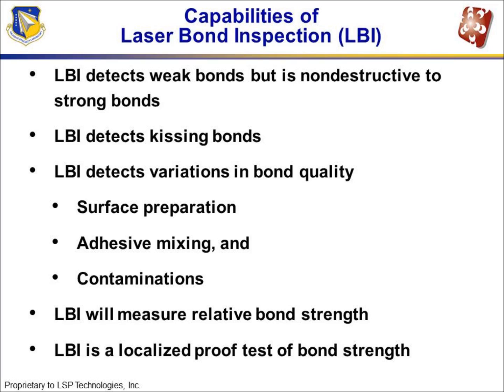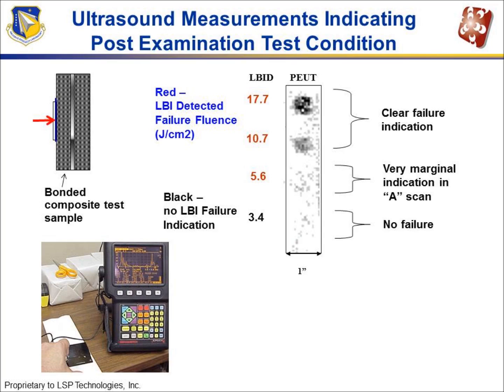By varying the fluence of the pulsed laser beam, we can modify how we affect the bond line. If you start off at a very low fluence, which is like 3.4 joules per centimeter squared, using ultrasound after the testing, we can see that there is very little damage to the bond line. As you gradually increase the fluence level, you see more and more damage until you get to a point that you have strongly damaged the bond line.